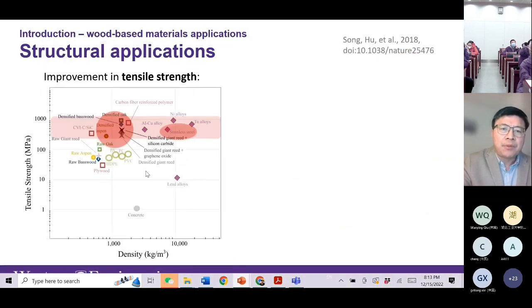Still from their group, they report this strong wood material in terms of tensile strength versus density. So for tensile strength alone, if you look here, the densified wood is in this circle here. And many alloys, for example aluminum copper alloys and nickel alloys, are actually at the same level of strength. But for density, wood has significantly lower density than the metals. So this makes wood a material with high strength and low density.